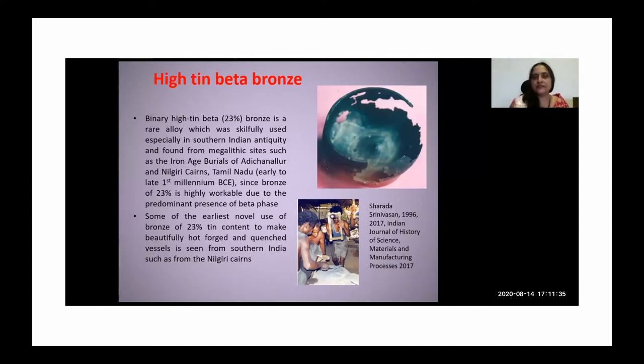But quite surprisingly, though I did talk about the low-leaded bronzes in the context of the Chola bronzes, there is also a very remarkable tradition of making highly skilled alloys in South Indian antiquity and also elsewhere in India, but it seems to have been particularly well developed and continuing in the context of Southern India from megalithic sites such as the Iron Age burials of Adichanallur and the Nilgiri cairns, which have been loosely dated to the early to late first millennium BCE. And these have been made by working a bronze of 23% tin, which has a predominant presence of beta phase, which I'll be explaining.